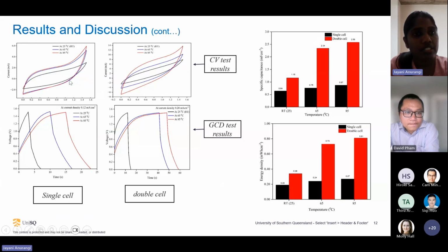When I talk about the CV test results, the area under the CV curve represents the capacitance of the structural supercapacitor. According to this value, you can see when the temperature increases, the capacitance has increased. And also according to the GCD test results, when the temperature increases, the energy density increases. Actually, it happens because when we increase the temperature, the kinetics and ion movements increase. That is the reason for the increase in the energy storage. And also according to these graphs, the double cell structural supercapacitor always has high specific capacitance and energy density. It is obvious because the double cell supercapacitor has 2 cells to store energy.